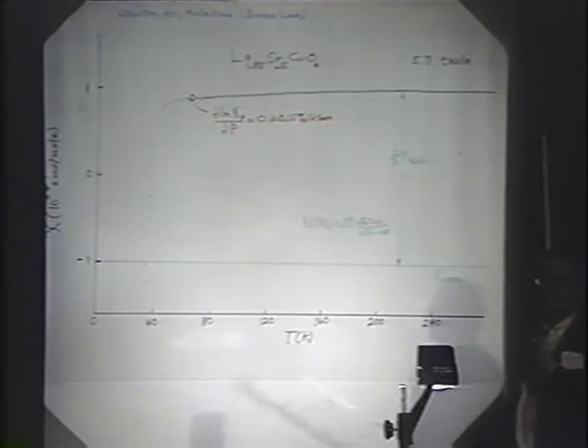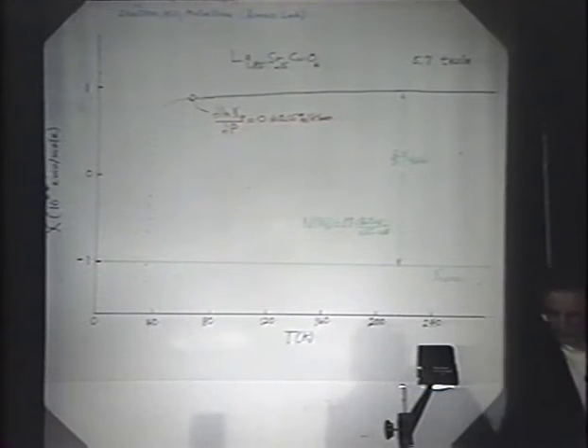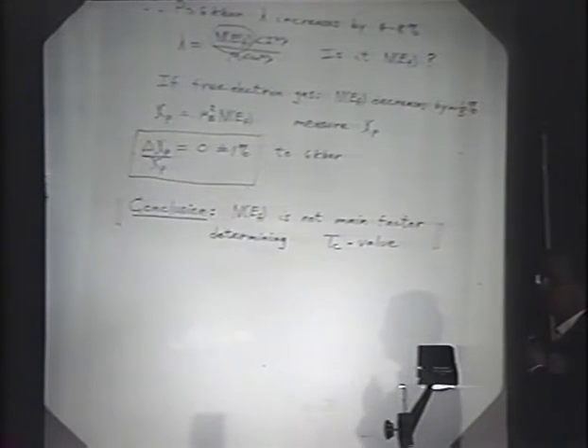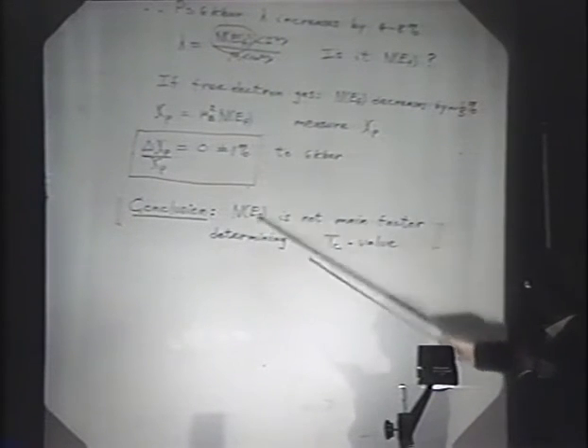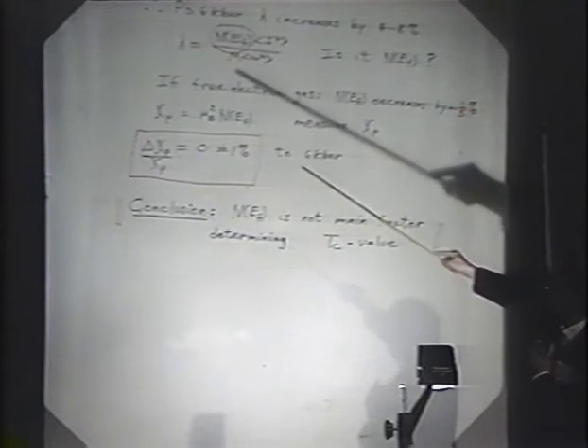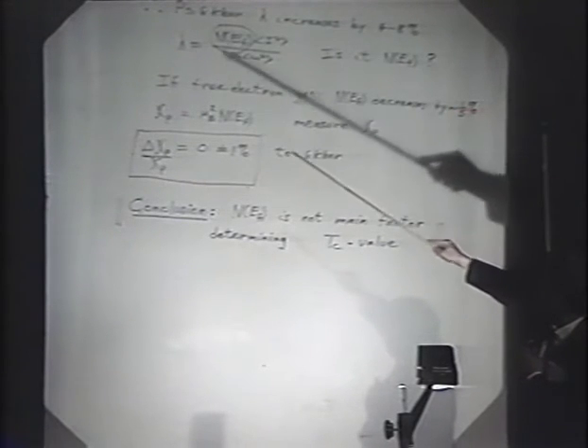The pressure dependence: we were unable to find any pressure dependence whatsoever in the susceptibility to this accuracy. And that means that at a pressure of 6 kilobars, we observe zero change in the susceptibility, that is, in the density of states, plus or minus 1%. And if the density of states increase had led to this lambda, then we would have seen it because this increase would have been 4 to 8%.